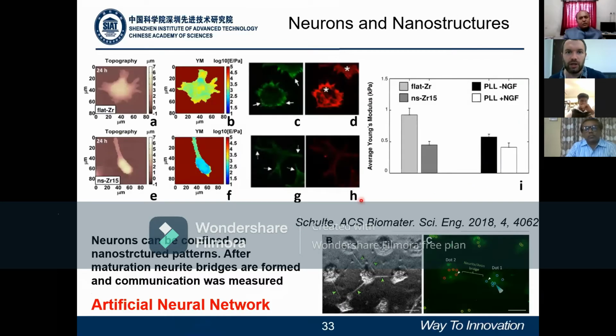And then finally here, I present something where we apply the cell on a nanostructured surface. So here, in some previous studies, we applied neurons on a nanostructured surface, like zirconia or titanium dioxide. And then we noticed, AFM noticed, that there is a decrease of the stiffness when applying on the nanostructured surface, plus without any chemical stimulation, the neuronal cell differentiates, producing neurites, which is an indication of maturation of the neuronal cell to the mature phenotype.